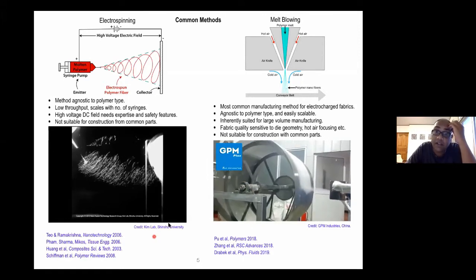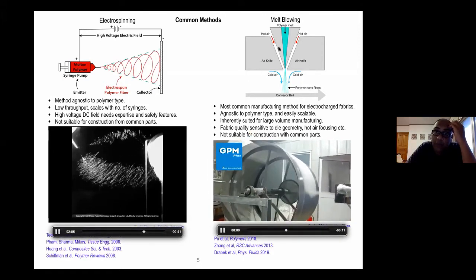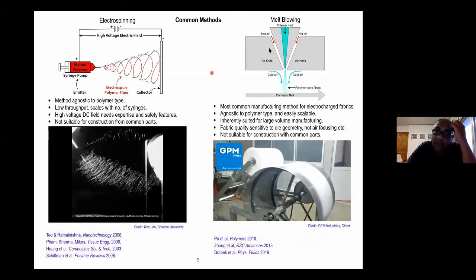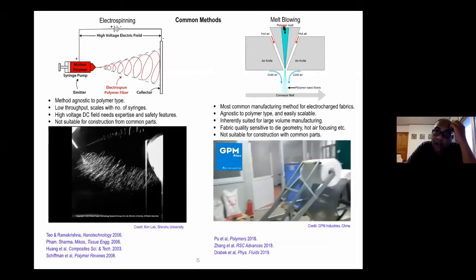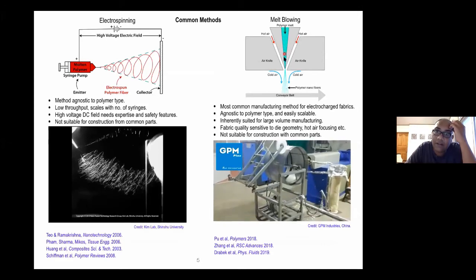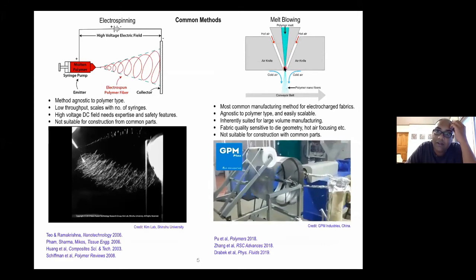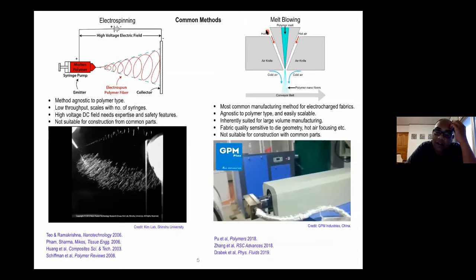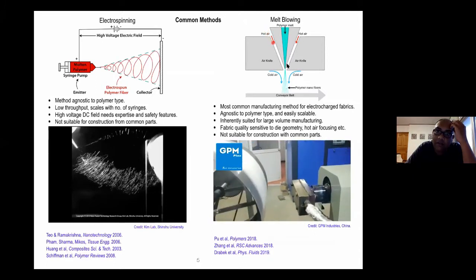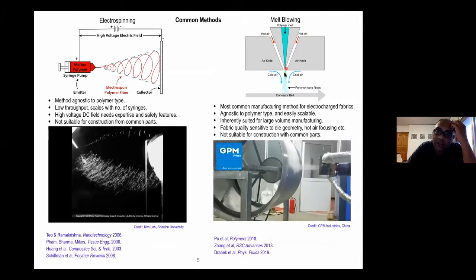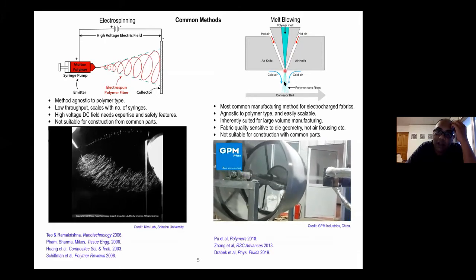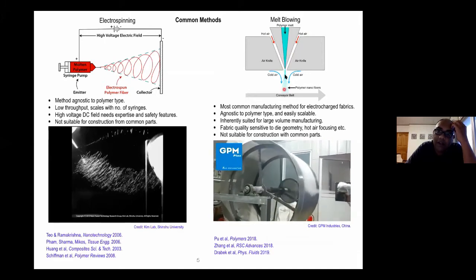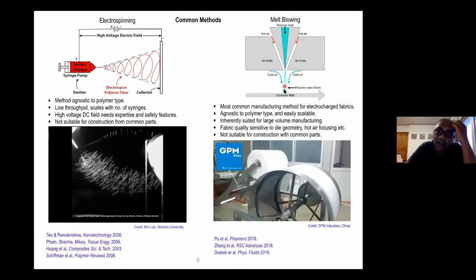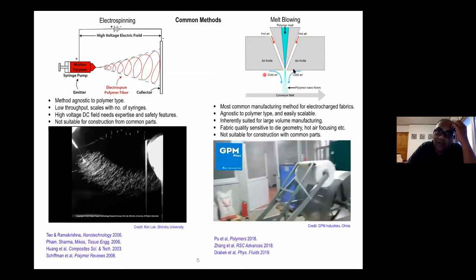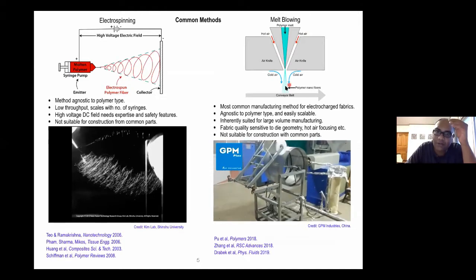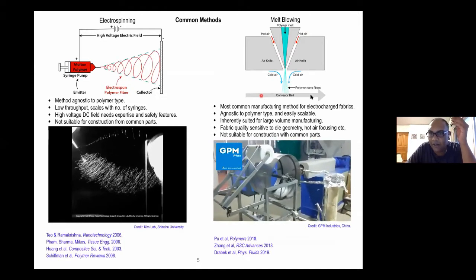The second method, which is actually the most common method used for manufacturing the electrocharged filtration layers for N95 respirators, is known as melt blowing. Melt blowing is basically where you have a polymer melt that is forced through a conical die with an orifice at the end, and you blow pressurized hot air from two sides to stretch the jet as it is coming out, and it forms a fiber. And as it is being accelerated by the hot air, there is a jet of cold air to cool it down so that it solidifies and lands on a conveyor belt.